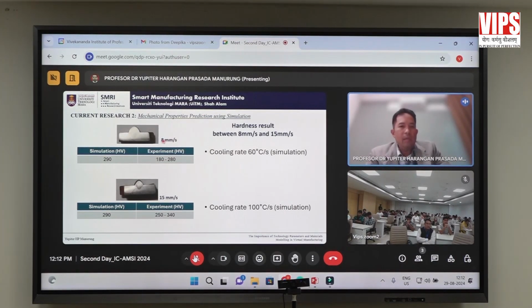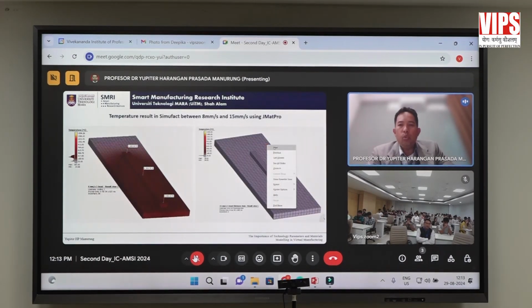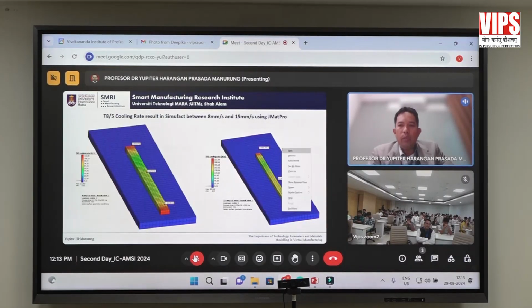You see here, with the 8 millimeter per second welding speed, and here is 15 millimeter per second. So here in the experiment we can get the 180 to 280 hardness figures. Here the simulations give 290. So something is wrong here, so we need to adjust. We need to improve our simulations. How do we improve that?